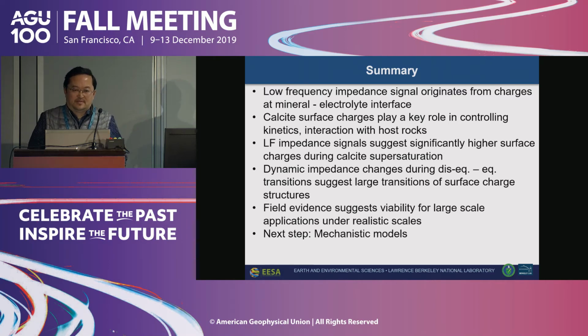Yeah, so that's right. Magnesium is considered one of the potential PDIs for the calcite system. We didn't run experiments in our study, but there are existing data that show if you add magnesium into the system, they behave very similar to calcium. So they will have an effect on the surface charge and the signal potentially. Yeah. Thank you.